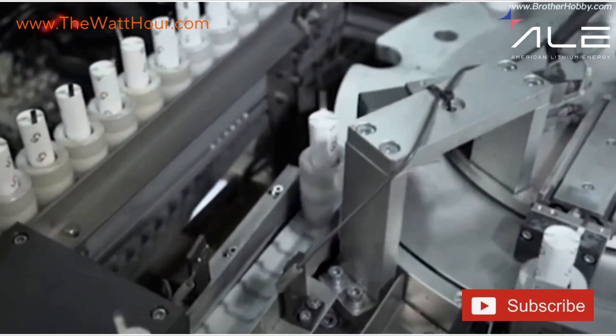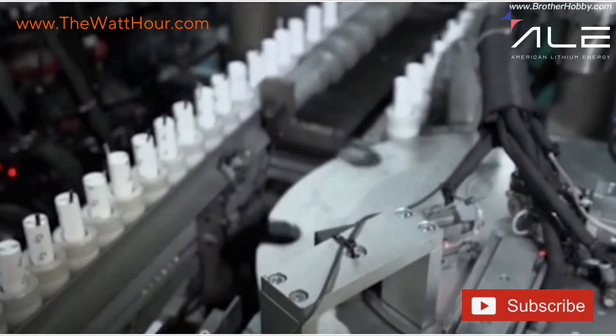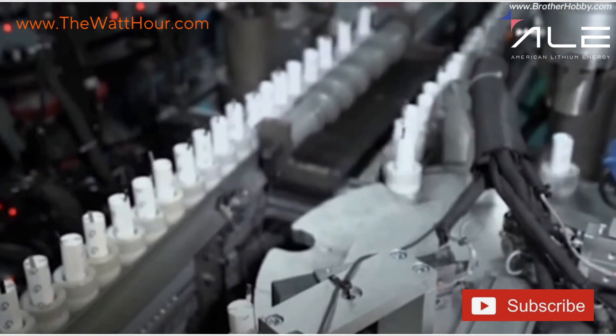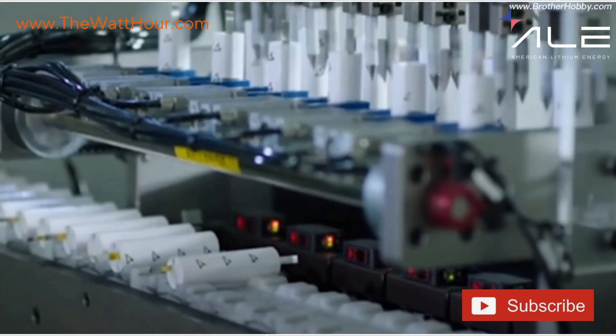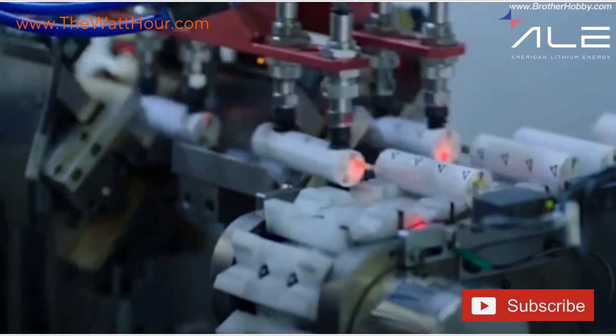We use high-purity electrolyte filling systems and hermetic sealing processes developed for aerospace-grade reliability. Once sealed, the cells rest while the electrolyte fully wets the electrodes, preparing them for activation. And then comes the most critical stage: formation and aging. This is where each cell comes to life. During formation, we carefully charge and discharge every cell under tightly controlled voltage and temperature profiles. The goal is to create a solid electrolyte interface — a nanometer-thin layer that stabilizes the anode and defines the cell's lifespan, safety, and performance.